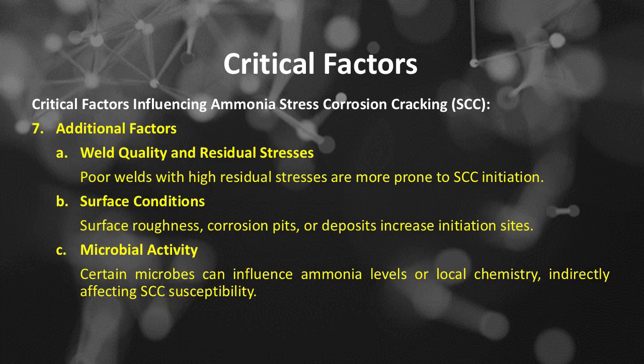Number 7 is additional critical factors influencing ammonia stress corrosion cracking, includes, number A, weld quality and residual stresses. Poor welds with high residual stresses are more prone to SCC initiation. Number B, surface conditions. Surface roughness, corrosion pits, or deposits increase initiation sites. Number C, microbial activity. Certain microbes can influence ammonia levels or local chemistry, indirectly affecting SCC susceptibility.